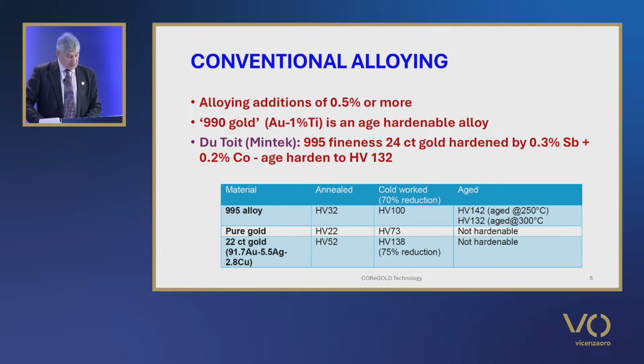Dutoit and co-workers at Mintek in South Africa showed that a 995 fine 24 karat gold containing 0.3% antimony and 0.2% cobalt can be age hardened to a hardness of 132-142 Vickers, depending on aging temperature, as shown in the table. And we can argue whether this is conventional or micro-alloying. My feeling is it's probably the latter.